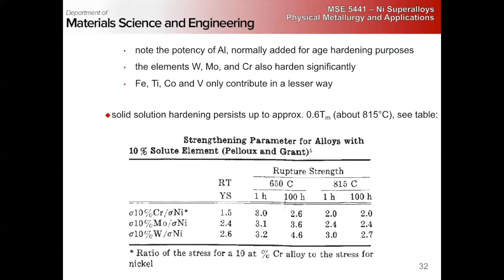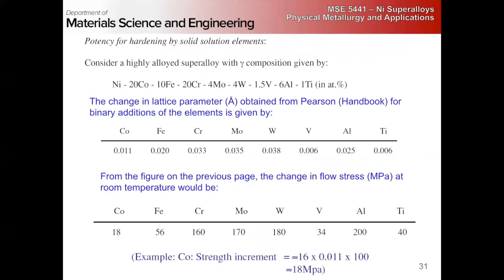On the previous page, titanium is not so high, but titanium for low stress. Yeah, so titanium's fairly low here. But it has a relatively small change in the lattice parameter, and the modulus is not significantly different. It contributes less. It's a stabilizer for the gamma phase. It's not necessarily a strengthener for it, right?